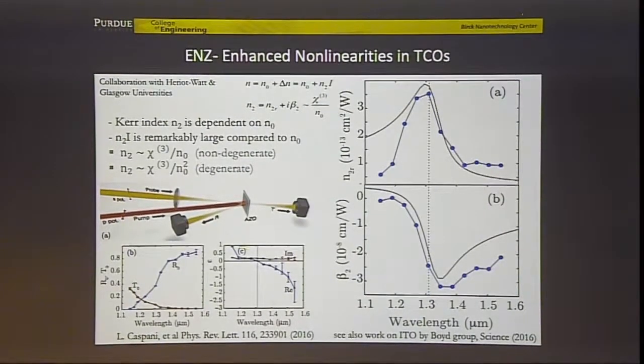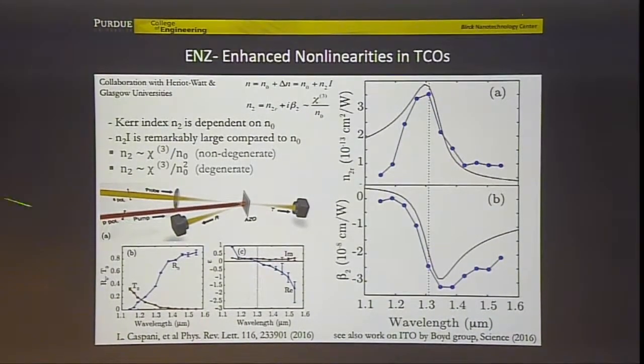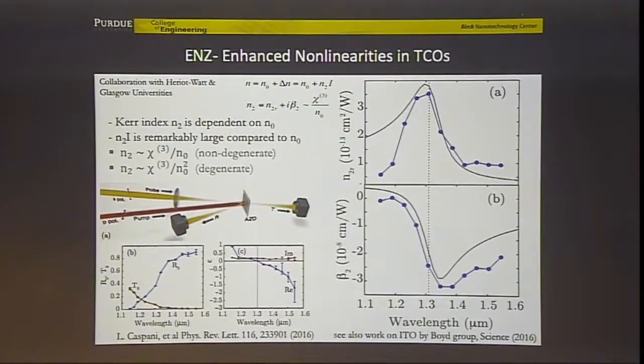At the point where epsilon crosses 0, where the linear refractive index becomes small, my nonlinear response jumps up. So this is low-index enhanced nonlinear response. To bring some understanding into this, you should realize that when you cross 0, you go from positive epsilon, dielectric, to negative epsilon, metal. You have a metal-dielectric, metal-insulator transition. So you dramatically change your optical properties. And anything is huge compared to 0. And our reference point here is 0.